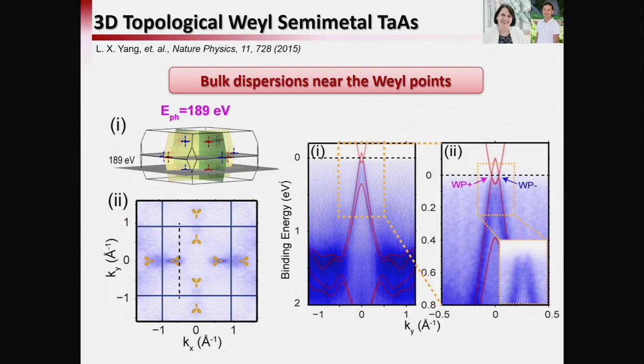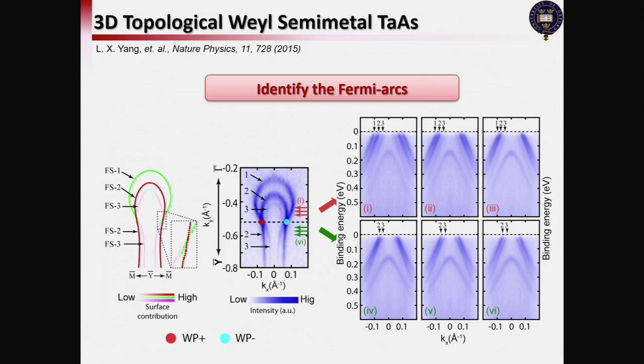And then, of course, the two Weyl points have to be connected by the surface Fermi arcs, and that's what we did. We located the bulk Weyl points, and then we changed the photon energy, etc., to change the experimental condition so that the surface state signal would be enhanced.